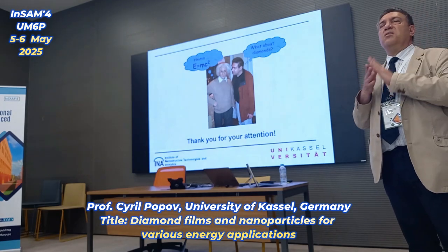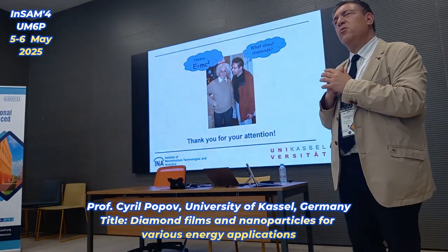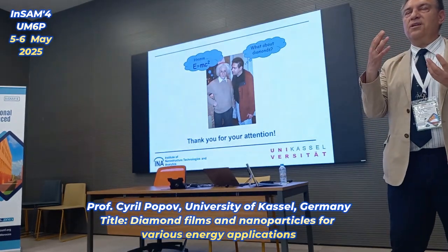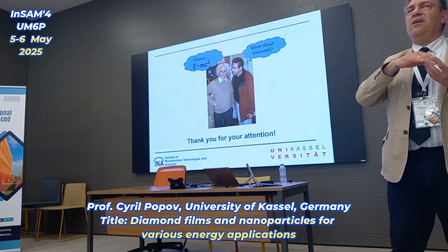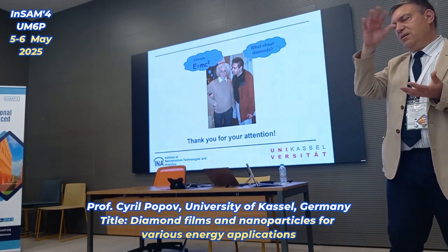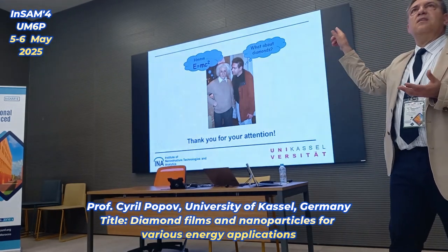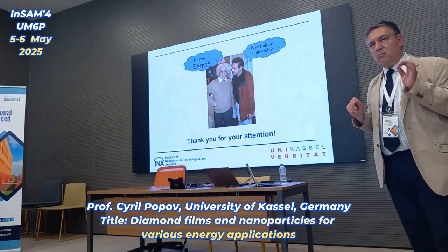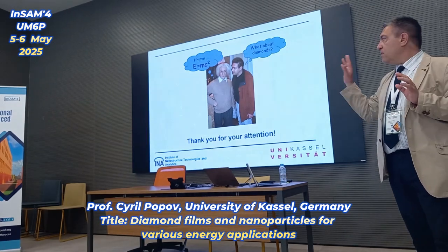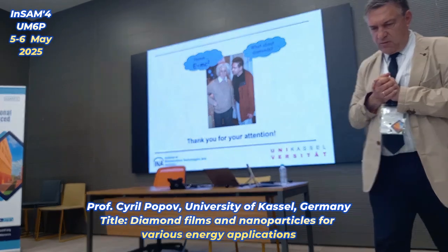In experiments, optical emission spectroscopy, if I remember correctly, was used to study in situ the species in the gas phase, how they change their concentration during the process, the initial stage, the final stage of deposition, and that's why they consider that the methyl radicals play the most important role, not CH2 or CH or even C. What kind of models can be performed?